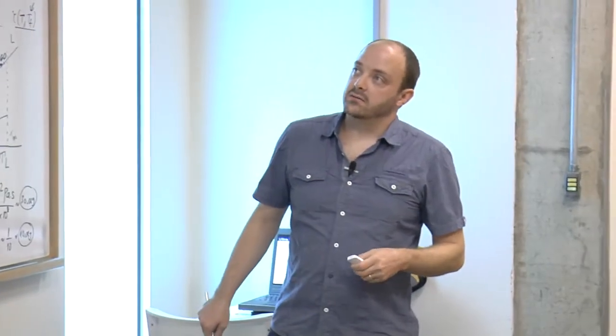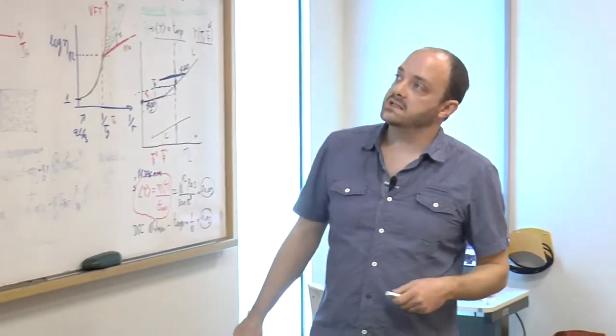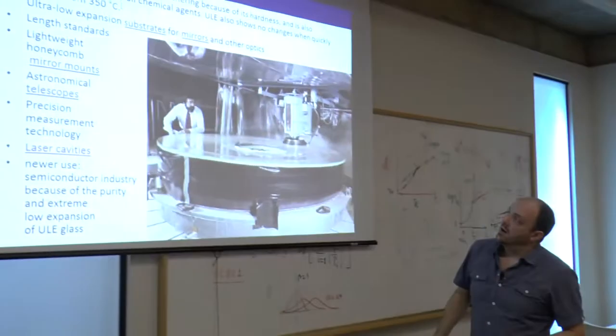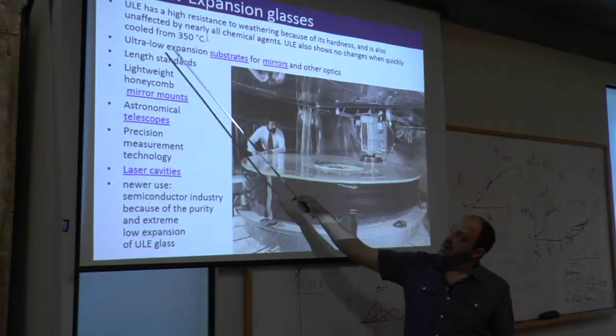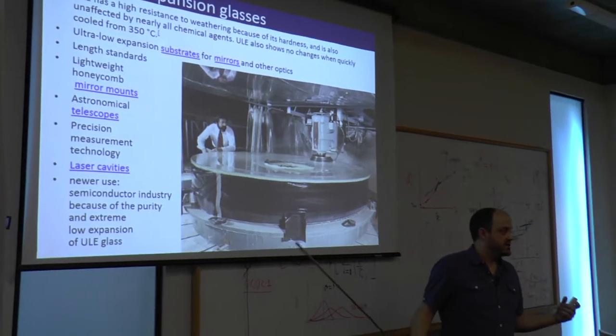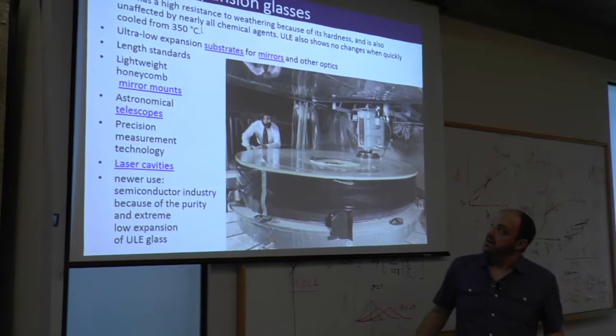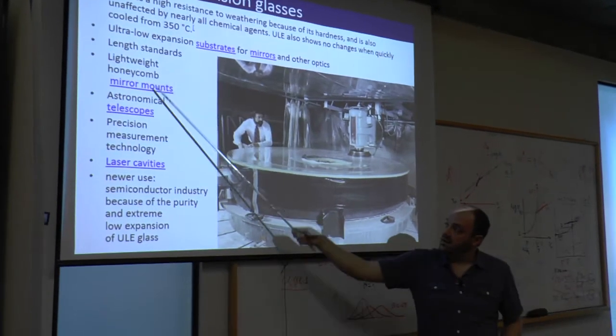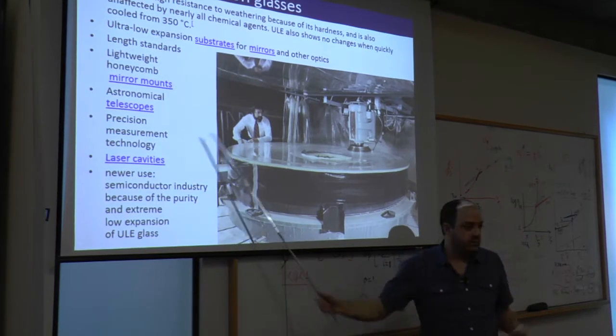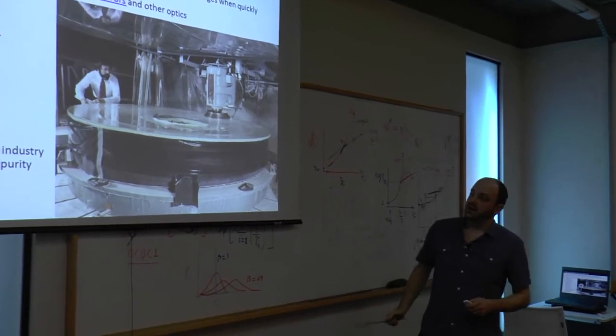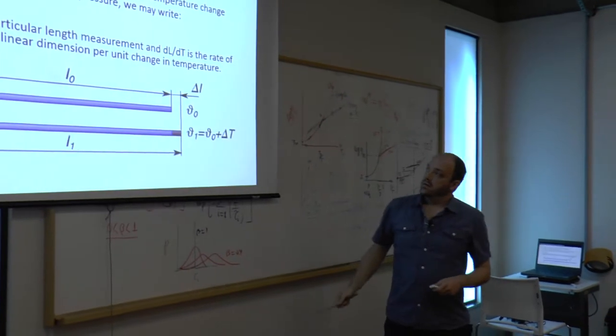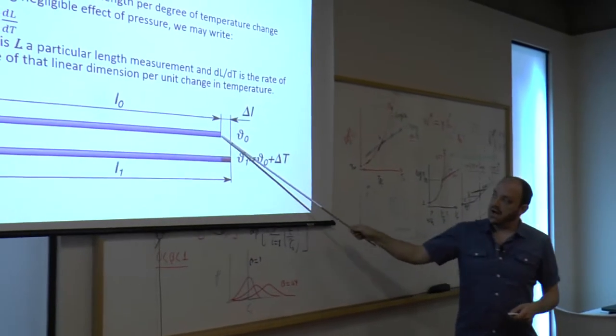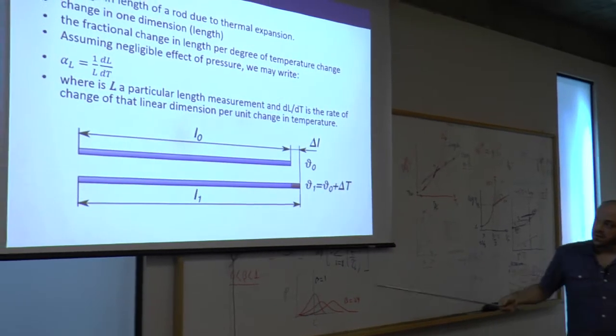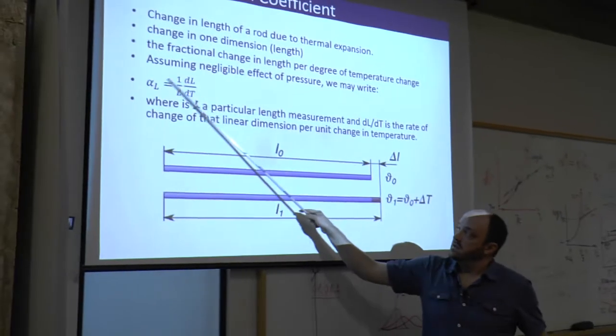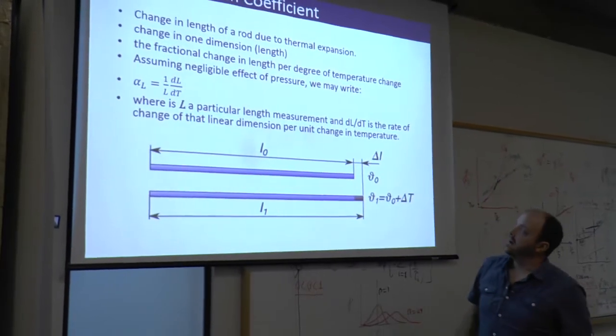Another glass that's quite silica rich are ultra low thermal expansion glasses. These have a lot of uses, but the key feature is that from -100 degrees to around 350 degrees, there's not much change in the expansion of the glass. So this is used for substrates for mirrors, particularly for astronomical telescopes, and for any measurement where you're covering a few hundred degrees around room temperature, and you need a very stable system. So the linear expansion coefficient is just how much this glass expands as you increase the temperature. It's quite straightforward, but the expansion coefficient is the inverse of the length times the change in length with temperature.